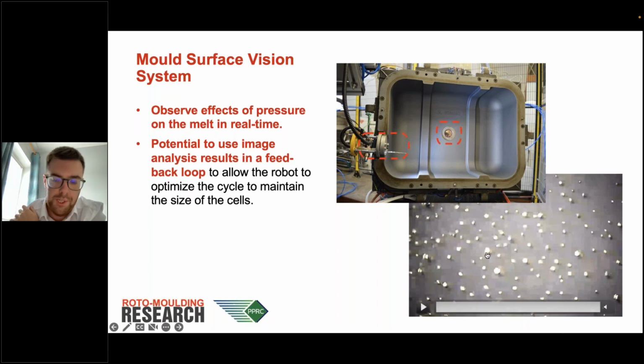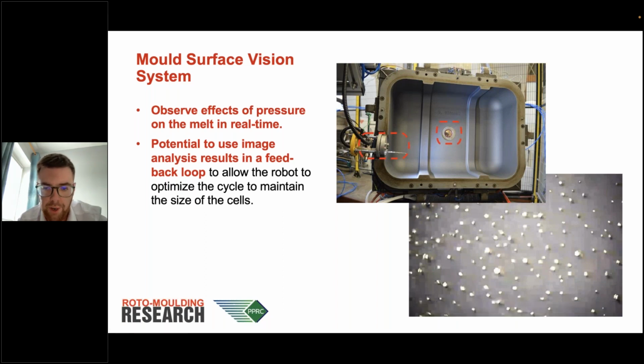But one of the nice things about that is that unlike using a chemical blowing agent process, you could program the robot so that you could have, for example, an input window that says what average bubble size do you want to see in your molding. So you could put 100 micron in this, and it would then control the pressure line to make sure that the average bubble size within the image that it was analyzing was within that region, which is something that you just wouldn't be able to do with a chemical blowing agent system.